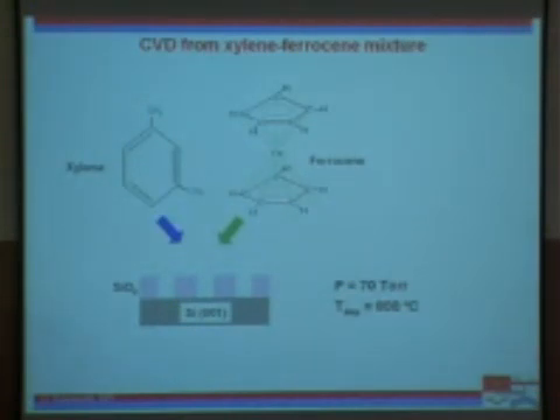So here we resort to chemistry, where nature does most of the work, and we just have to get lucky by trying the right kind of things. We use a precursor where we have a carbon source and a catalyst which is delivered from the gas phase. And this catalyst selectively interacts with silica, SiO2, to the exclusion of silicon, and produces growth of carbon nanotubes only on silica.